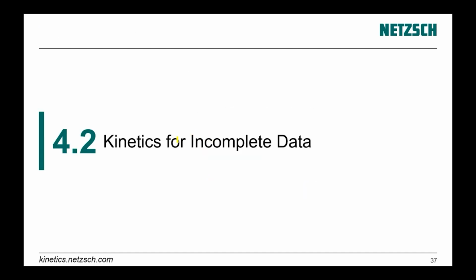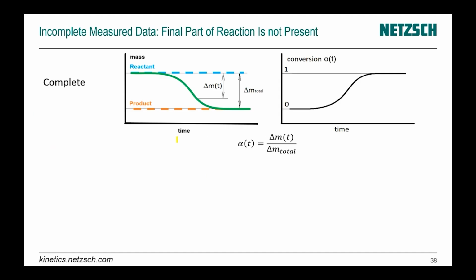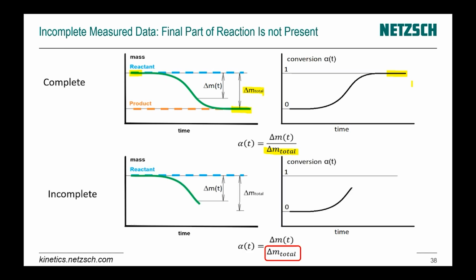The next point is kinetics for incomplete data. The data are complete if before measurement we have only a reactant and after measurement we have only the product. Then a reaction is complete and completely measured. And then from the last point of the measurement, we can take a value of a total effect of reaction and we can use it for the calculation of degree of conversion. And then the last point of conversion curve is the value which corresponds to the total reaction, to 100% of reaction. We recommend to have always complete data, but sometimes it is impossible.